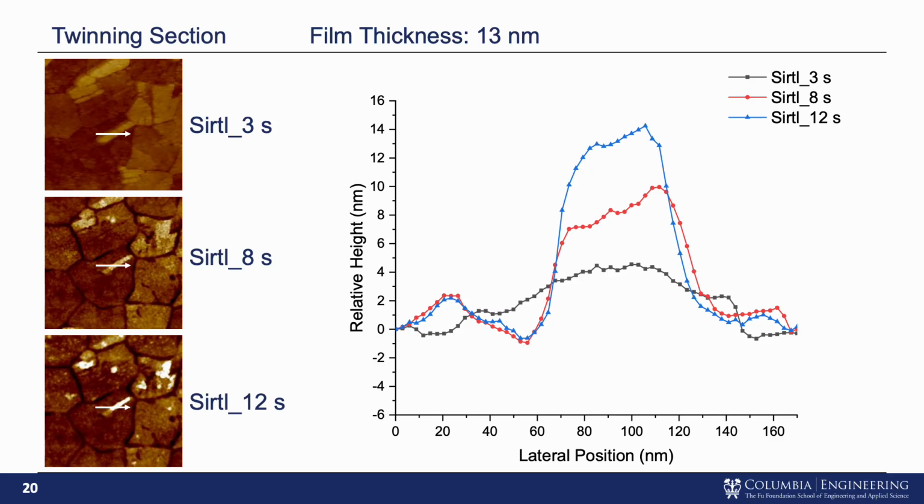One explanation is that the etching rate of the twin plane itself is relatively low compared to the surrounding grain orientations. In addition to becoming taller, the twin-related feature also becomes narrower and steeper with increasing etching time. One possible explanation is that the etching is not uniform across the neighborhood of the twin. The material adjacent to the twin plane is removed faster than the center of the twin, so the sides retreat while the core remains.